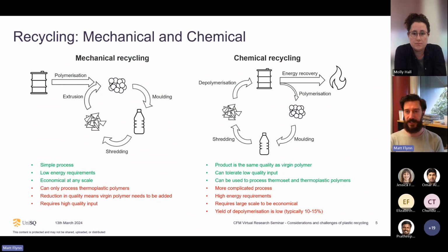The flip side is chemical recycling. And so the products that come out are the same as the virgin polymer, because you turn it back to a monomer, you can refine it, and then you can generate your polymer that's the same quality. It can take relatively low quality input. It doesn't need to be as clean. It doesn't need to be as finely sorted. And it also can deal with thermoset polymers, which mechanical recycling can't do, same for using as a filler in your polymers.